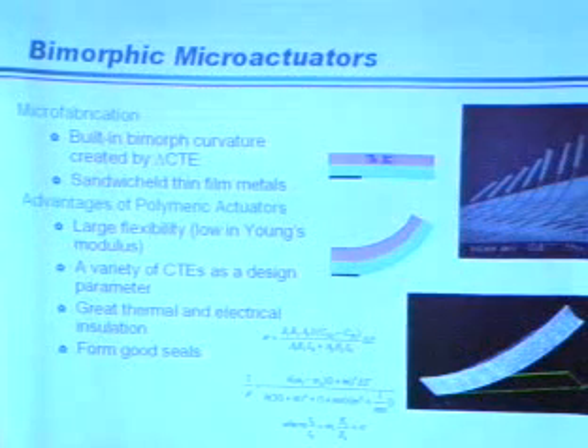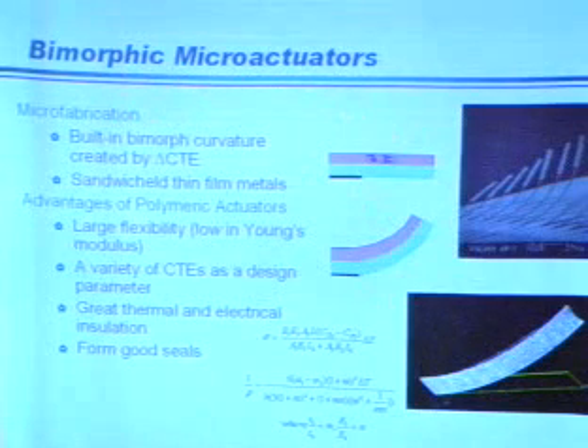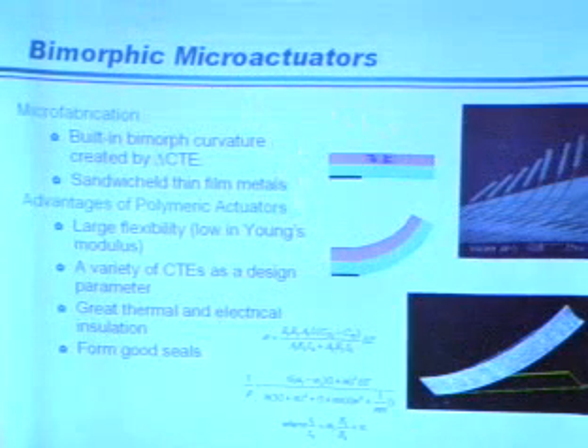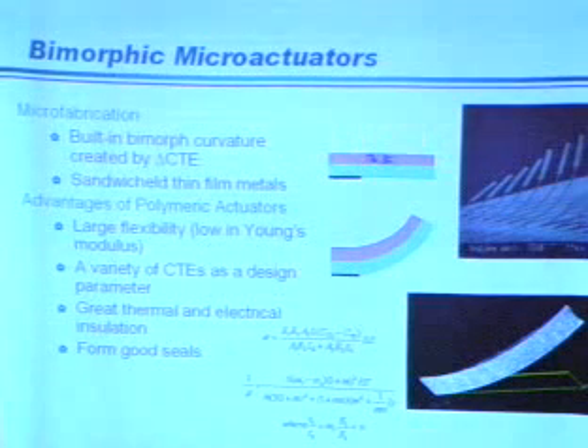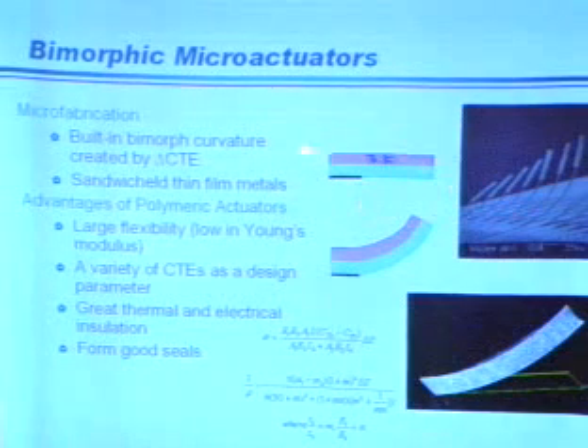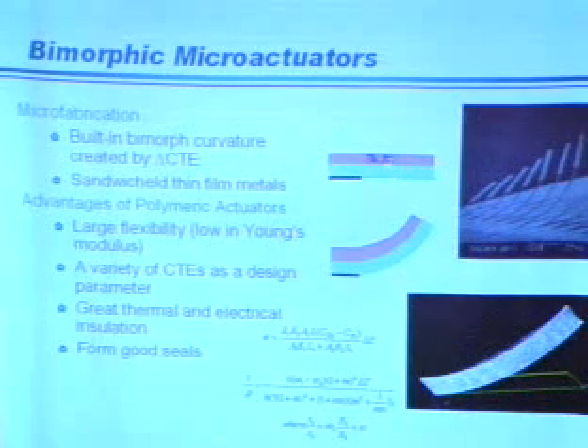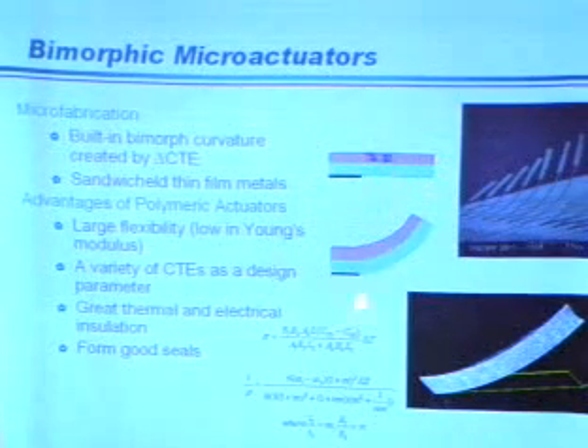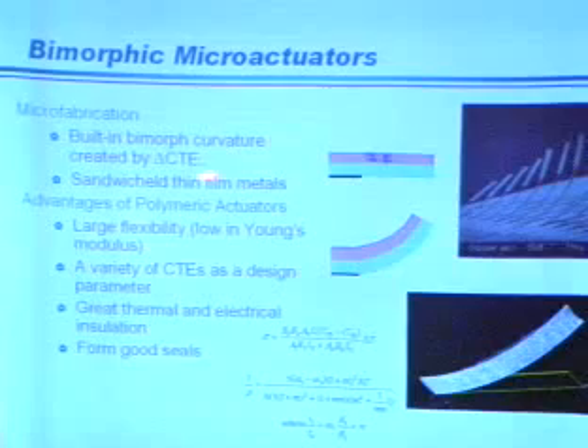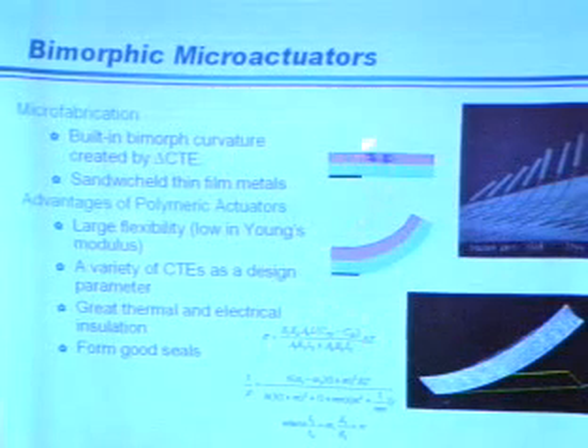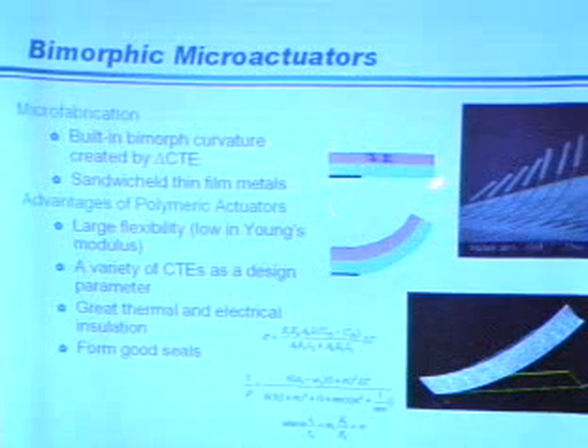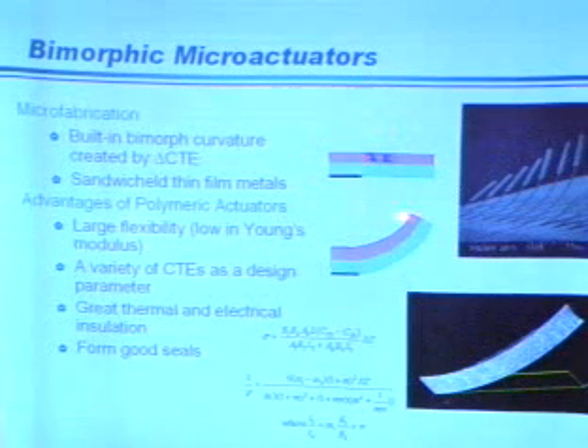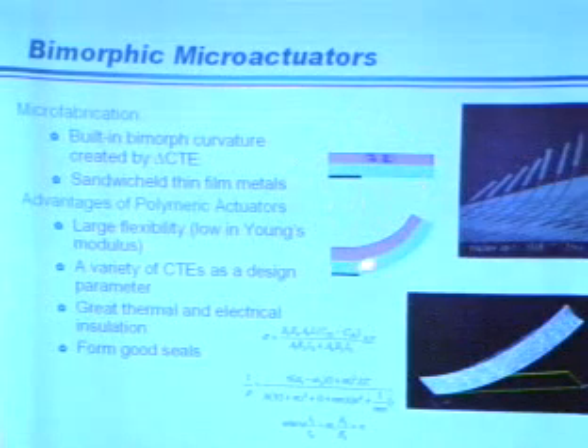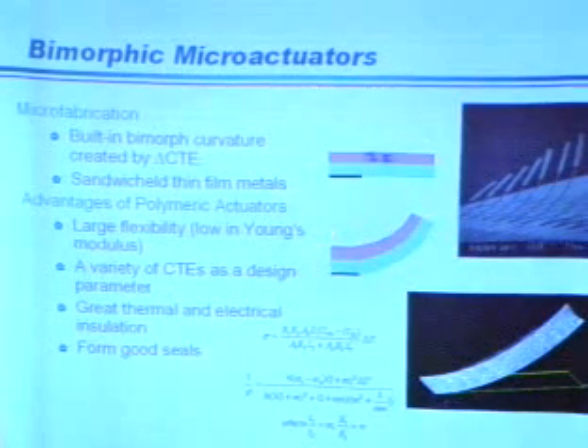And then a couple more actuators that I just mentioned. We actually focus a lot on bimetallic or bimorphic actuators. The reason being, these are very simple theories. Basically you just take thin films, a lot of which is developed extensively by the semiconductor industry. You can develop the right kinds of thicknesses and have different material properties. DuPont and other chemical companies allow you to design in very many parameters. Mainly the two parameters are the coefficient of thermal expansion and the stiffness, the Young's modulus. Once you put these thin films down and you have annealing or a temperature difference, it allows you to generate a thermal residual stress, and that will curl up this so-called bimorph cantilever.